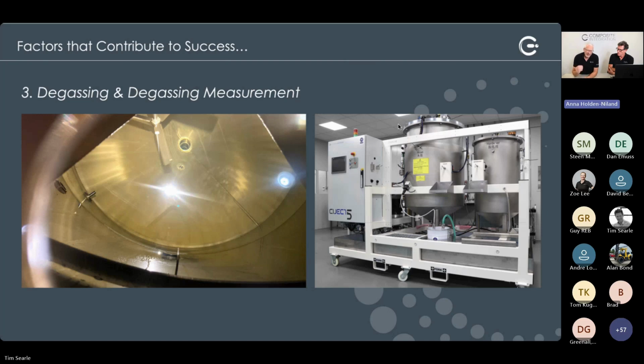And we can see from the clarity of that resin, our gut feel is that that's a really well degassed resin, and in truth we know if we've got that clarity it's pretty good. But what we also get now from our measuring system is that we can see the rate of improvement of that degas over time, and we can reach a threshold at which not only does the resin look really clear as it does in that tank, but actually we know that it's properly degassed and will make a high quality laminate when used.